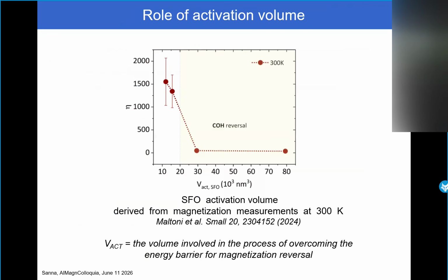I can also show you this by plotting the enhancement factor as a function of the activation volume for the SFO counterpart, derived from magnetization measurements by Pierre, Davide, and co-workers, where the definition, of course, of the activation volume is the standard one, the volume involved in the process of overcoming the energy barriers for the magnetization reversal. And you can see that the enhancement factor drops to the standard value expected when the activation volume is higher than a threshold limit that I'm not going to show you here, that is of the same order of magnitude